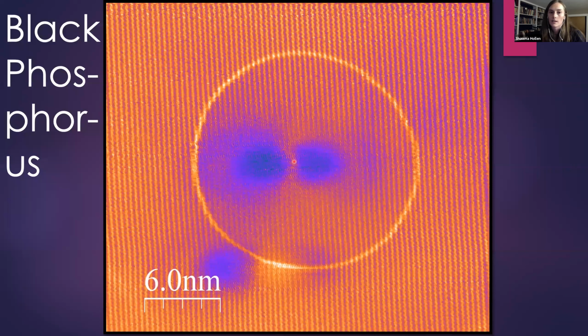So this is why studying defects can be really important in materials, because if you have one missing atom and you have this big electrostatic cloud from this one missing atom, then if you were to try to use this material for technological application, like for instance, a transistor, you would have a lot of issues with the quality of the material and how easily electrons will move through the material. The mobility of your semiconductor will suffer because of these kinds of effects. So STM can tell you about those local changes to the electronic structure that happen because of defects.